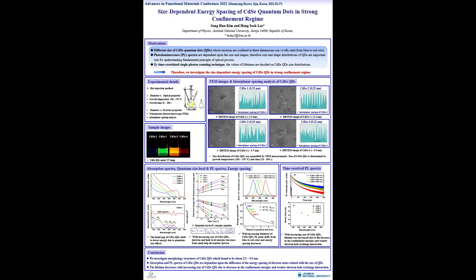When compared to energies of electronic transition of cadmium selenide quantum dots, we calculate electron and hole level energies using the quantum size level equation. As cadmium selenide quantum dot size decreases, electron and hole level energies increase, and we can determine the orbital state of electronic transition of cadmium selenide quantum dots.